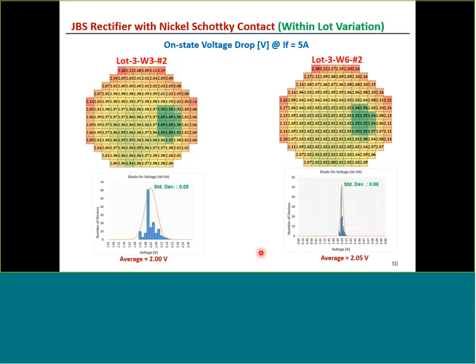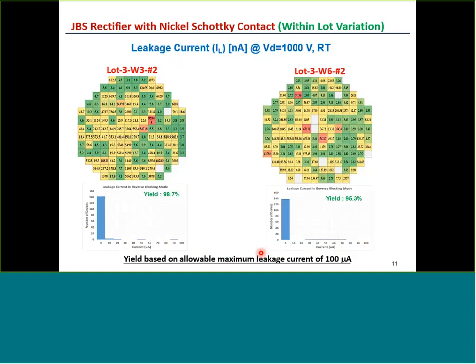And the conclusion is that the average value is about 2 volts for the forward drop on our diodes, and the distribution is very tight. The standard deviation is quite small.